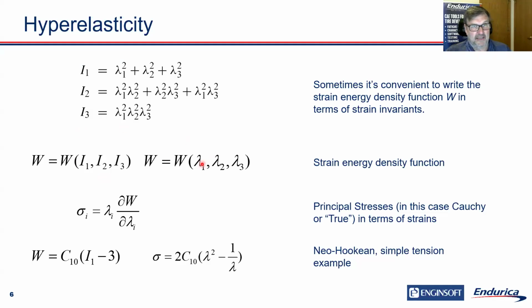Sometimes it's convenient to write this not in terms of the lambdas directly, but in terms of strain invariants. So here are these strain invariants listed, but it's the same kind of result. We're looking at what's the strain energy density in terms of the deformations of the specimen or the product. Once we have that function W, you can differentiate it with respect to the strains, in this case with respect to the stretch ratios, and get a stress-strain relationship.